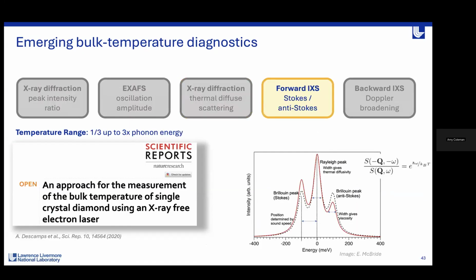Finally, these last two techniques are meV inelastic X-ray scattering techniques. For forward meV IXS, we're measuring temperature through detailed balance, looking at the asymmetry in the phonon spectrum. meV resolution measurements at small momentum transfer, where Q is the momentum, allow us to resolve the Stokes and anti-Stokes phonon peaks.